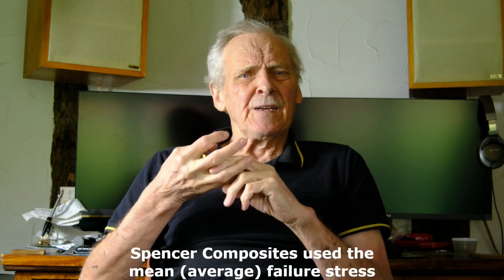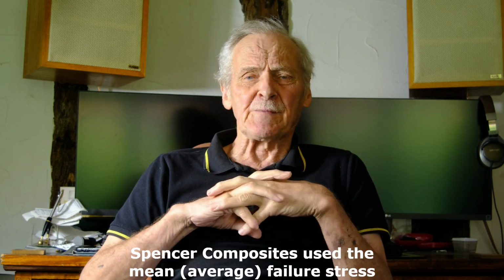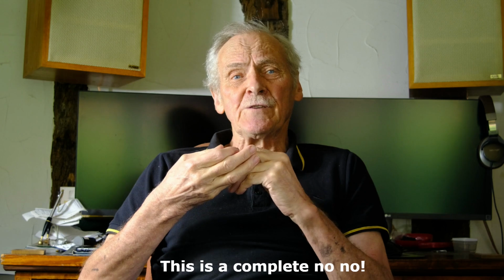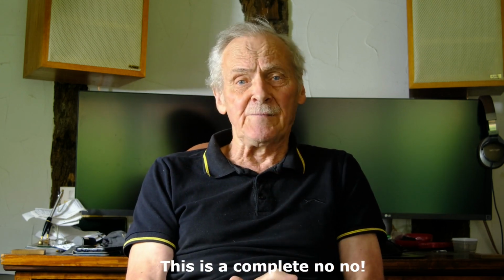So my first question is, how did Spencer Composites decide which values to use? Did they merely select the data which gave all the high numbers? But the second point, you never ever use the mean failure stress when you're characterizing a material. What you do is you compute what's called the characteristic strength of the material, and this is almost always defined as being the mean minus 2 standard deviations. It means that 97.5% of the values will lie above the characteristic strength, but 2.5% will lie below, and this is taken care of through the safety factor. So I have huge questions about the failure stress assumed by Spencer Composites for design purposes.